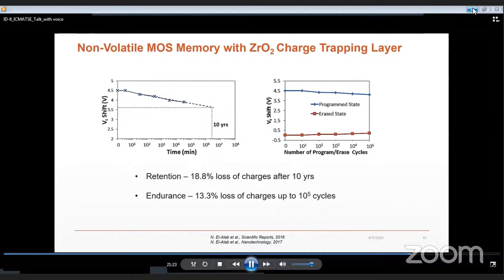The retention characteristic of the memory is also analyzed by first programming it at 5 volts and reading the state in time. The extrapolation to 10 years reveals a 3.65 volt shift in the threshold voltage, which means that around 18.8% of the initial stored electrons are lost. So this indicates that the electrons are well confined in the quantum well.